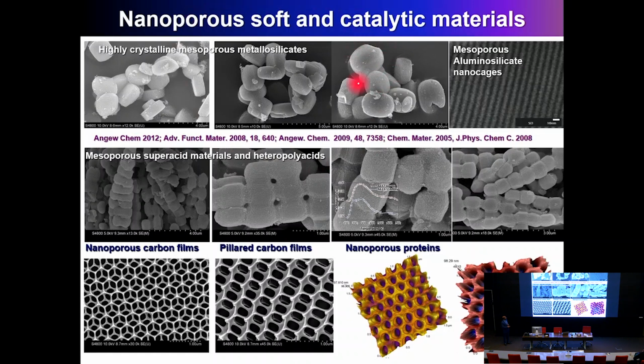And all these materials are in powder form, but we can make such materials in film form as well. And some of them are shown here. Carbon films with hierarchically ordered structures and even biomolecule nanoporous films, cytochrome C, lysozyme, and so on. So these are all fascinating materials, from hard materials to soft materials, even to living molecules. So we can introduce highly ordered nanoporosity with a very high surface area. The question is, can we use these materials for solving the global issues?